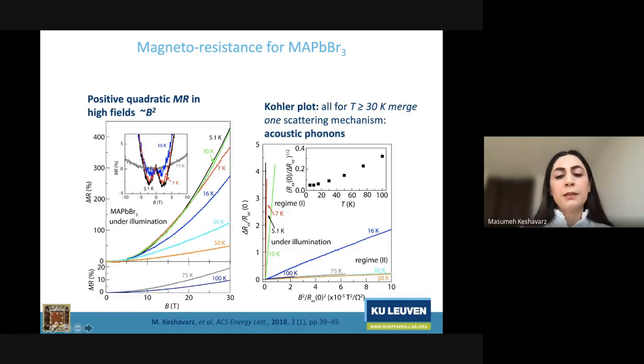If we measure the magnetoresistance as a function of magnetic field, normalized to the zero field resistivity, this is referred to as a Kohler plot. In the Kohler plot, all the curves at different temperatures which are merging are following the same scattering mechanism. We see that below 20 K the curves are merging on each other, and above 20 K they are also merging with a different slope. This is another indication that we have two distinct regimes here.